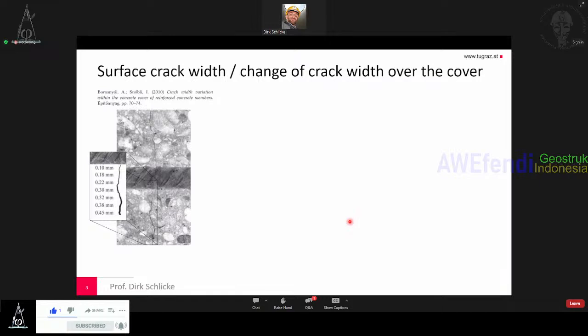To get a bit closer into the topic, we can look at the experiment of Borosnyói and Snóbli from Hungary. They made a reinforced tie, as you can see here. There's the concrete cover. This is the rebar already sawed. So they cut the specimen, tore it apart, produced a crack, filled the crack with epoxy, and then they cut it. Something similar was done 40 years earlier by Goto.